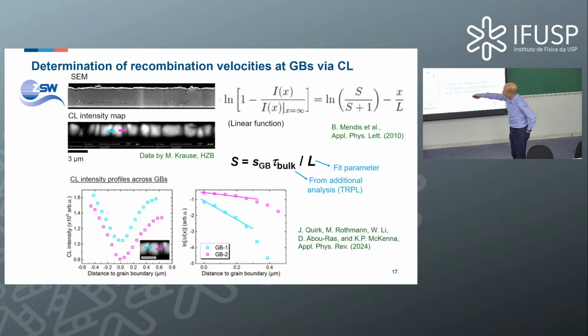And then what we do is not to look at the difference between the grain interior and the grain boundary in terms of the CL intensity, but we look at the logarithmic change. Because what we want to do is to obtain a linear function, showing basically how strongly the intensity decreases towards the grain boundary. And how strongly it decreases tells us something about the recombination velocity. This is the model, right? And in order to do so, what we have here is a reduced recombination velocity. This is the capital S. And the capital S actually consists of the real recombination velocity, S_GB, the bulk lifetime in the grains, which is the lifetime of the charge carriers, and the effective diffusion length, which is used as a fit parameter for the linear function.